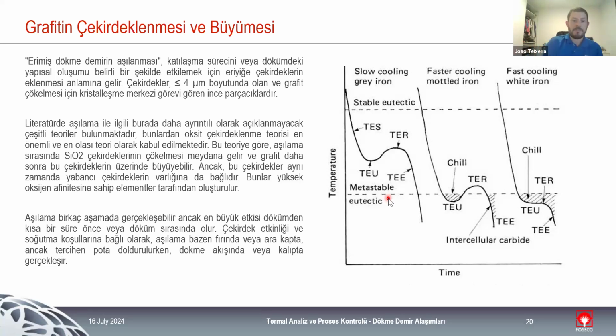Because even if the inoculation step is really, really good, if you have a good inoculant agent, but we have a high amount of these elements, we'll probably have a lot of carbides, because the affinity of carbon is really high with this type of elements. So it's easy for carbon to go and grab these elements that are free in the melt. So we need to play with both areas, with a really good base metal, with a low amount of these trace elements, and choose the correct inoculant for the process that we are going to have.